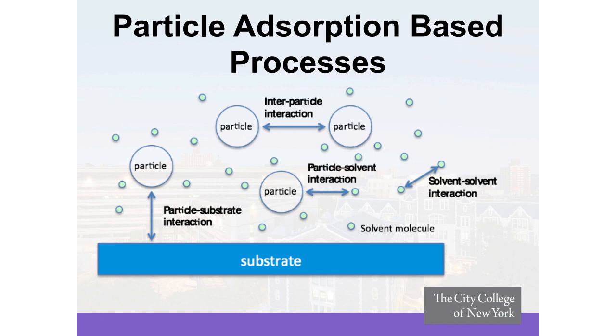The final project that we are very interested in the lab deals with particle adsorption on surfaces, and one can very easily understand these types of interactions that occur when a particle approaches a substrate. Whether it will adsorb or not on that substrate depends on the specific interaction of the particle with the actual substrate. It will also be determined by the particle-particle interactions as well as the particle-solvent interactions and the strength of the solvent-solvent interactions. This set of 4 interactions pretty much determines the extent of adsorption of a particle onto a substrate.